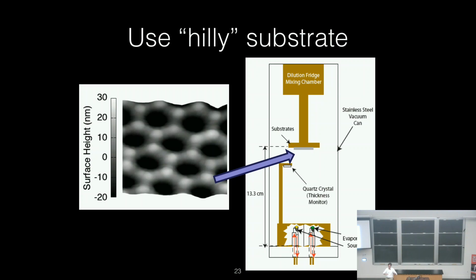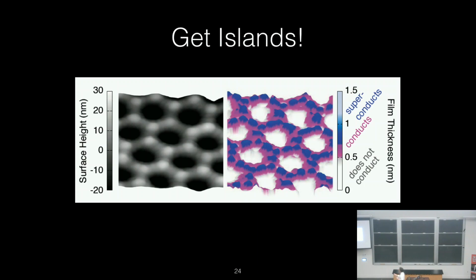Because of cosine theta, you know, the whole cosine theta, the flux thing, right? The thicker films are superconducting. We can tune it this way, and the thinner ones are not. So we actually wind up with something that we're pretty sure looks like this, where the blue areas are superconducting areas, and the magenta areas are not. We've made dots.